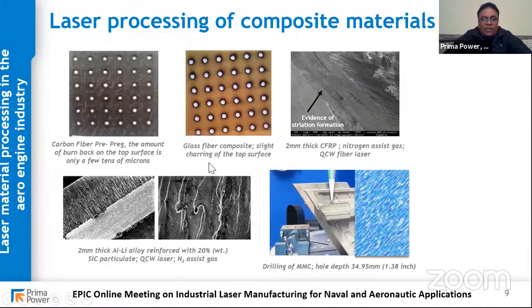Another thing which is gaining a lot of interest is composite material, which is plastic composite or metal matrix composite. So this is one example of the video, which is a metal matrix composite. The hole depth is about 35 millimeter deep. And this is actually percussion drilling. And you can see it takes about 10 seconds to drill the hole. The actual depth of the hole is about 35 millimeters, which is about 1.38 inches.